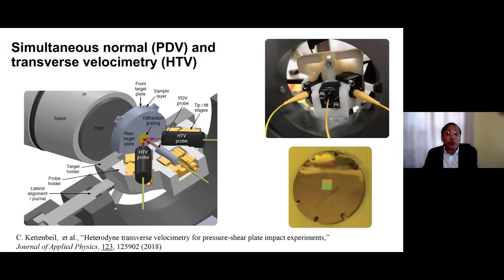The second thing we had to do is to have a robust measurement of the free surface velocities. As I should have mentioned earlier, there is a diffraction grating deposited at the rear surface of the sample, and this is where you probe to measure the normal and transverse velocities. To increase the robustness of the measurements, we have taken photonic Doppler velocimetry, PDV, and created a system where you can do heterodyne transverse velocimetry, so that we can measure both normal and transverse free surface velocities using photonic Doppler velocimetry techniques.